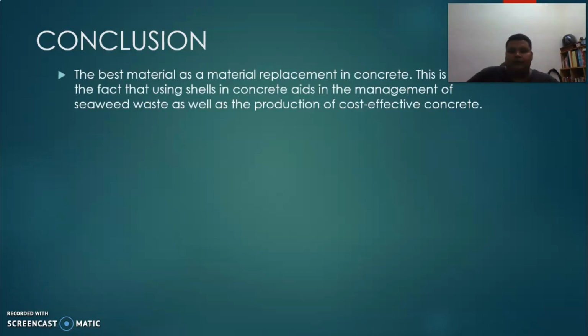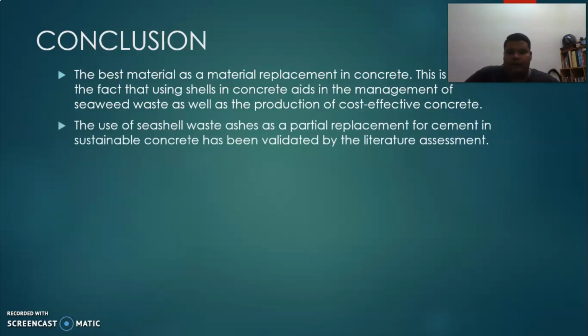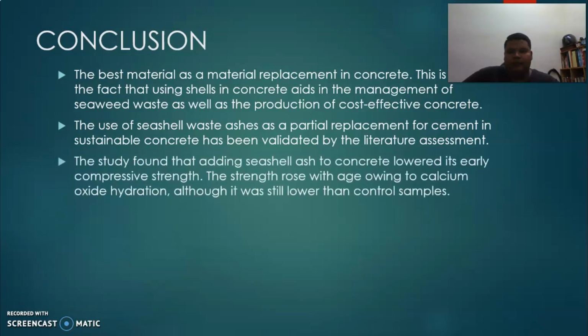Seashell is the best material as a replacement in concrete. This is due to the fact that using seashells in concrete aids in the management of seaweed waste as well as the production of cost-effective concrete. The use of seashell waste ash as a partial replacement for cement in sustainable concrete has been validated by the literature assessment. The study found that adding seashell ash to concrete lowered its early compressive strength. The strength rose with age owing to calcium oxide hydration, although it was still lower than control samples.